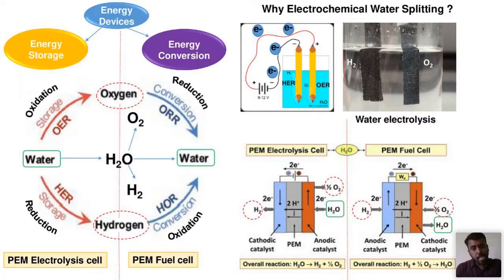For example, in the case of electrochemical water splitting, you need two electrodes, and you have to supply an overpotential higher than the thermodynamic potential, that is 1.23 V. You can connect to a 9 or 12 volt battery, and with the transfer of electrons, the splitting of water will happen. Hydrogen evolution will happen at the cathode, and oxygen evolution will happen at the anode. Some bubble generation will occur at both anode and cathode.